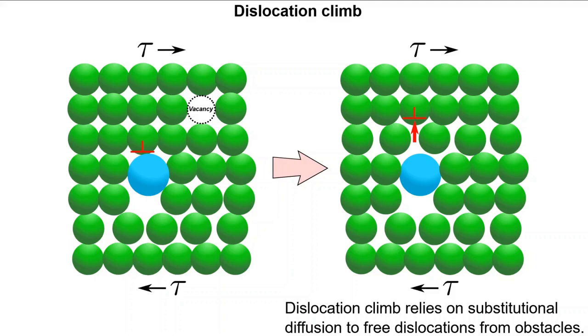The role of vacancies either moving or being generated at higher temperatures also explains why grain boundary strengthening diminishes at elevated temperatures for polycrystalline materials. These are naturally spots which contain a large number of vacancies due to the misorientation in the originating solidification event. Therefore, materials which contain a large number of grain boundaries will be particularly susceptible to creep. And this also explains the behavior of the long wire versus the short wire demonstrated earlier. On a cross-sectional basis, both wires will have roughly the same number of grain boundaries, but over their lengths, there are significantly more grain boundaries on one versus the other.